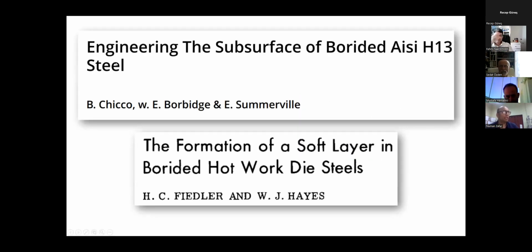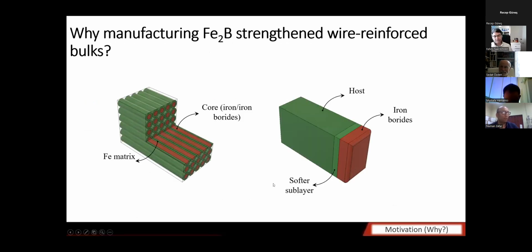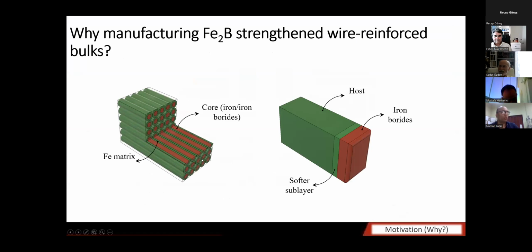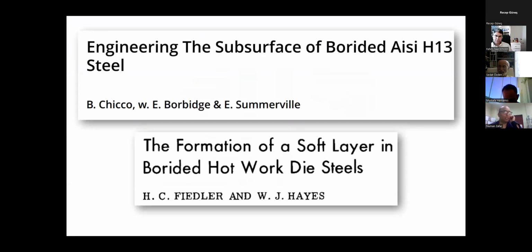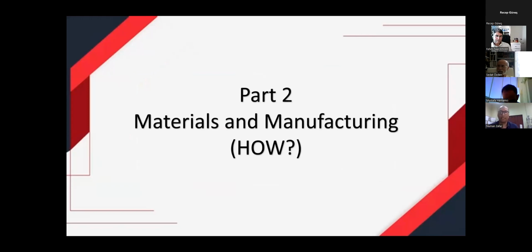Here are some studies which have attempted a different approach to control the subsurface of borided steels. Here is a formation of a soft layer which is reported in the steels, a softer sublayer. In such a material, something like that will not occur. Your material will be more uniform? Yes, it will be more uniform, also because I am not using a steel which has many elements inside, where I need to take care of each element differently. I have used low carbon steel, so something like that is not going to occur in this proposed material. Then it could be cheaper, maybe? Of course, yes, it is cheaper. So just put forward the positive sides. Yes, okay.